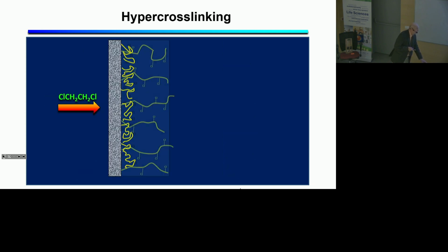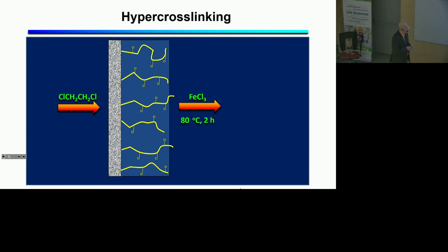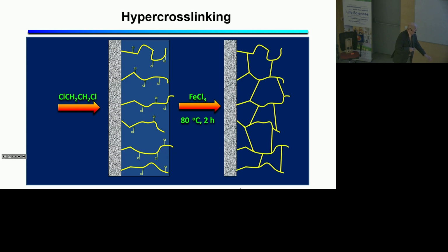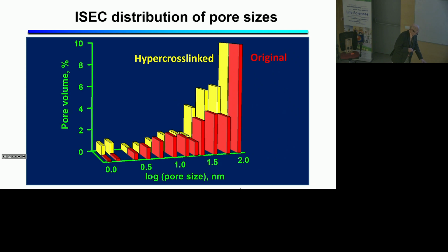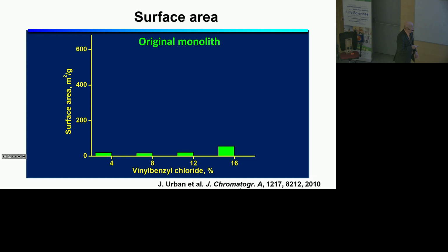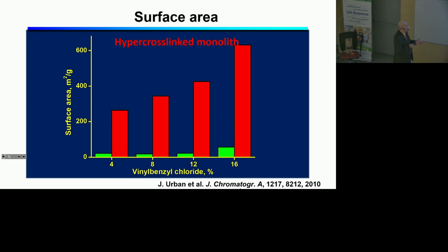So what we can do, we essentially swell this system with a good solvent, dichloroethane, and once the system is swollen, we cross-link these swollen chains using Friedel-Crafts reaction, and we are getting much smaller pores, which has a big advantage because it immediately increases the amount of small pores, like in this area. This is a logarithmic scale, so don't worry too much. As you see, this is the original monolith, this is the hypercross-linked counterpart, and we see that the quantity of these pores is increased quite significantly. From the beginning, we have about, depending on the vinyl benzyl chloride present in the system, about, I don't know, 10 square meters per gram. After the hypercross-linking, we can go up to 600 square meters per gram, which is significantly larger.